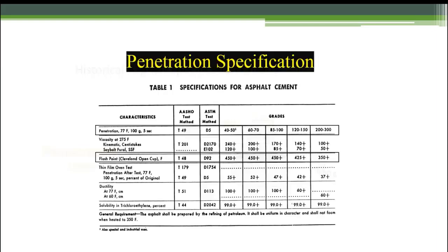So this is the actual AASHTO specification, the penetration graded asphalt specification for asphalt cement. There are two things, and hopefully everybody can see these okay. I put a box around primarily two things. One is the penetration, and you can see that's the upper line there. Penetration at 77 degrees Fahrenheit, 100 grams, 5 seconds. So just like we looked at in the previous schematic. The test method itself is AASHTO T49, and then there's the comparable ASTM test method. But it separated it then into 5 grades of paving grade asphalt: 40 to 50, 60 to 70, 85 to 100, 120 to 150, and 200 to 300. That's a distance that needle penetrates into the asphalt.